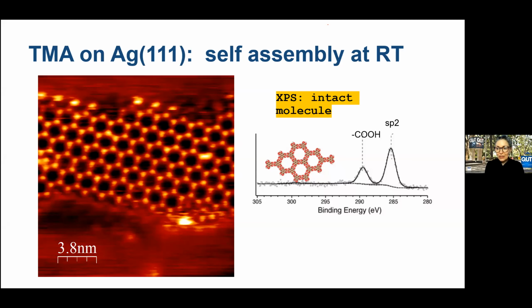What it does allow me to show you, though, is that there's a very clear spectral signature of this molecule in X-ray photoelectron spectroscopy. In particular, the carbon 1s core level contains information about the central sp2 hybridized carbon ring, so that's the benzene at the center of the molecule, and it also contains information about the functional groups. When we have intact carboxylic acid, it appears at a binding energy about 4.1 electron volts above that primary peak. This allows us to use XPS to measure the chemical state of the molecule precisely. So our intact molecule does exactly what we would expect and dimerically bonds into the chicken wire structure.